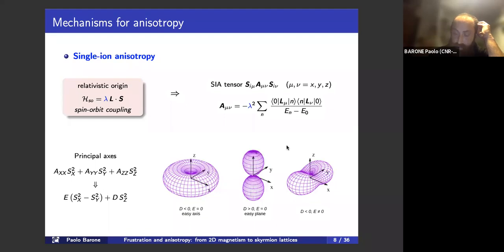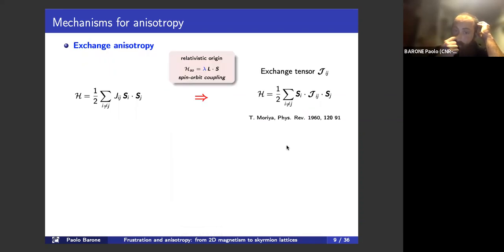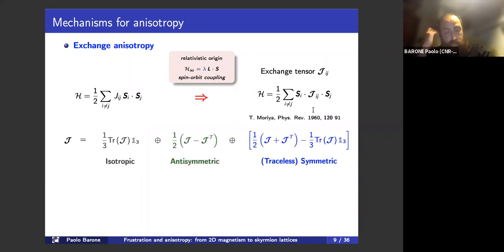Now, the point is that spin-orbit coupling is also responsible for the anisotropy of the exchange. And this also was realized by Moriya in the 60s, where basically he included the spin-orbit coupling in the superexchange perturbative derivation of the exchange coupling. And of course, due to the presence of the spin-orbit coupling, the scalar exchange coupling constant must be transformed into a tensor. Now, a tensor can always be decomposed in these 3 terms.